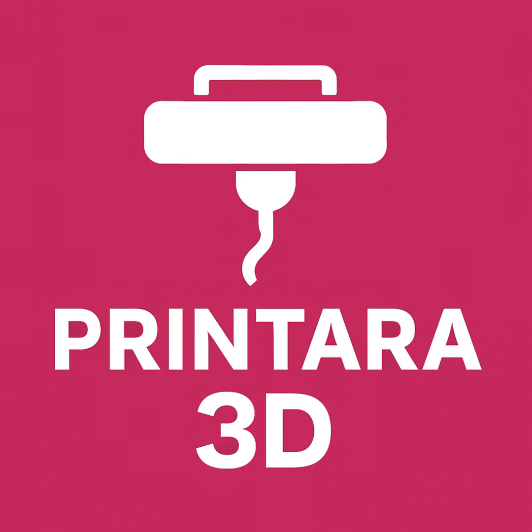So how do we actually fix it? You have to aggressively dry the filament before printing. Right. You can use a dedicated dryer box like a Sunlu S2. You can repurpose a food dehydrator, or you can use a standard kitchen oven set to 50 to 70 degrees Celsius for 4 to 12 hours. Though I always add a massive warning regarding the kitchen oven method.